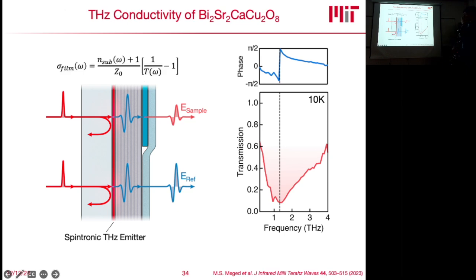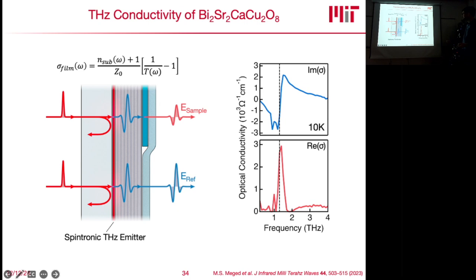So these are our direct measurement coefficients. There's really nothing done with this; this was just algebraic transformation. What we can now do is take the so-called Tinkham equation, which is only valid for a very thin film. Since we are here in the regime of 20 to 30 nanometers, we can consider it to be a thin film. We can take this analytical expression, plug in our frequency-dependent transmission, and calculate the frequency-dependent conductivity of this material, the terahertz conductivity. And this is shown here. What we'll find is that in the real part of the conductivity, you get a very strong peak.